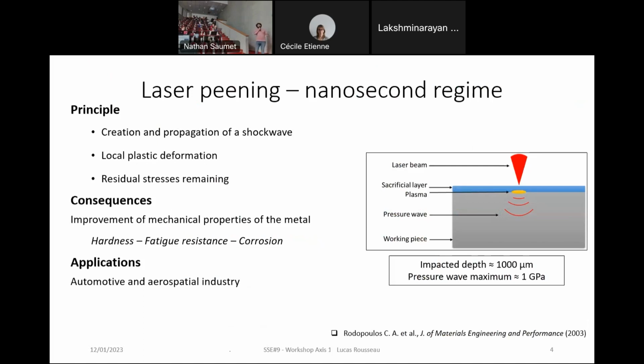So this technique is already well known and industrialized. One of its drawbacks is that there is a need for a sacrificial layer on the surface of the treated material in order to confine the shock wave and take it into the bulk.